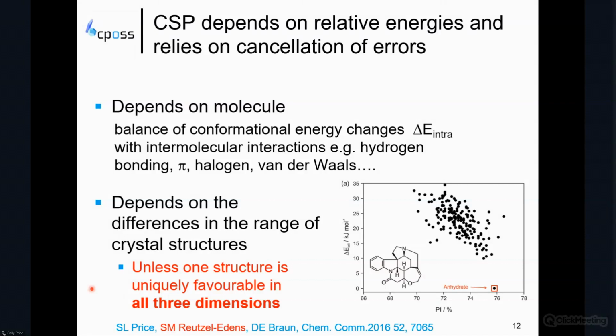Here's strychnine, where there is such a large energy difference of about 10 kilojoules per mole between the lowest, which is the only observed crystal structure, and the rest, that you can be pretty confident it won't be polymorphic, and it doesn't really matter how accurately you calculate that large difference. But this we now understand to be rather rare because it requires the packing of your molecule to be uniquely favorable, defining all 3 dimensions of your crystal structure.